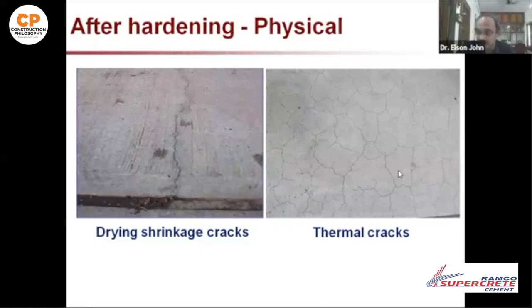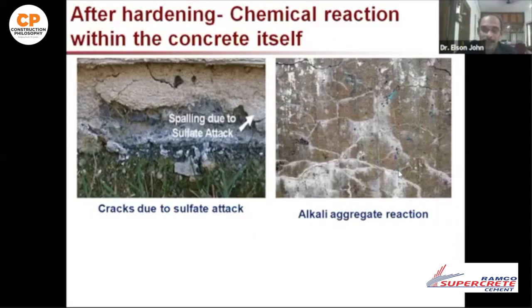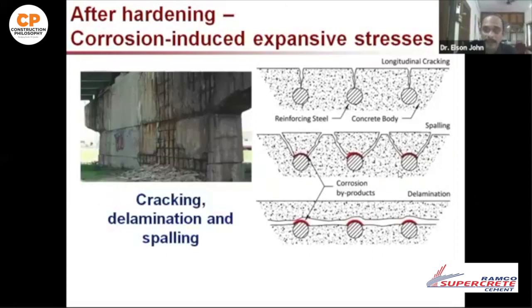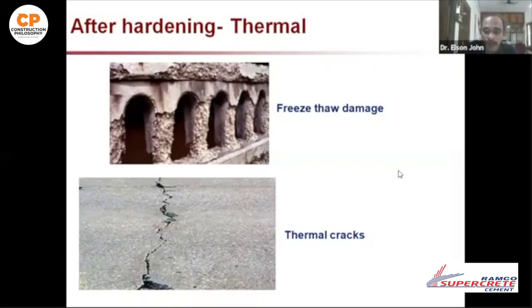Then subgrade changes, then drying shrinkage, that is removal of water from the pores in the concrete. Then thermal, especially for mass structures: the inside temperature of the concrete will be high and the surface is exposed to the atmosphere, so there will be a temperature gradient, and that can lead to cracking. Then sulfate attack and alkali aggregate reaction, where you can see map-like cracking in the structure. Again, corrosion of the reinforcement: when the reinforcing steel corrodes, its volume expands, and that exerts pressure on the concrete and can lead to cracks and spalling.